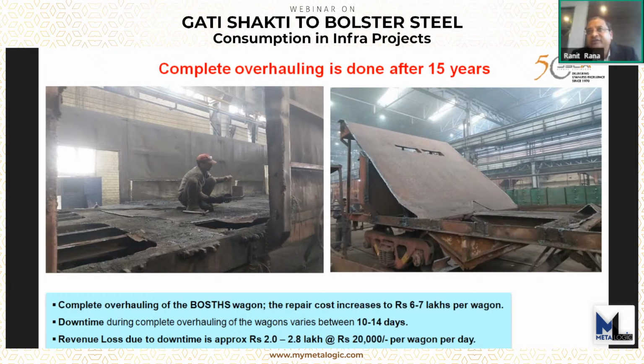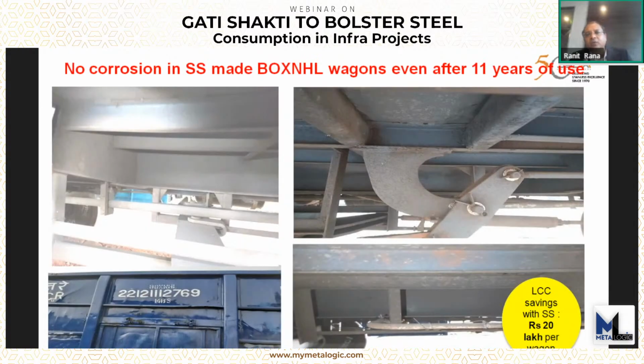And I understand that Indian Railways consider the downtime as 20,000 rupees per wagon per day. So the revenue lost during the downtime is almost 2.8 to 3 lakhs. And if we look at the overall cost because of corrosion repair over the total life of the wagons, it comes to about 23 to 25 lakhs. Now, during this visit, we have also tried to understand the corrosion which is happening in a typical stainless steel made wagon.